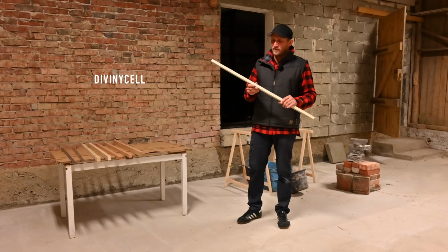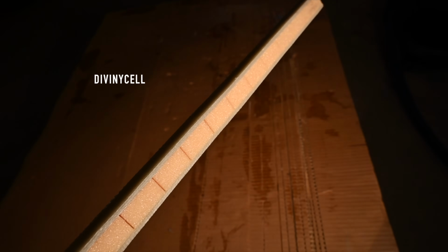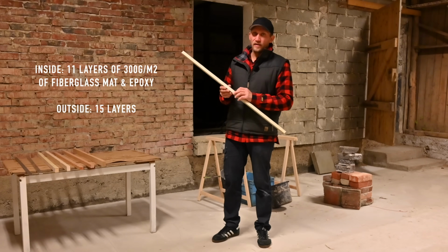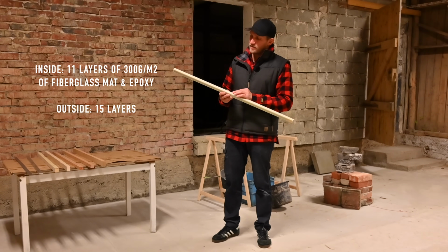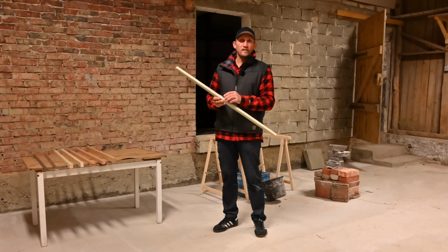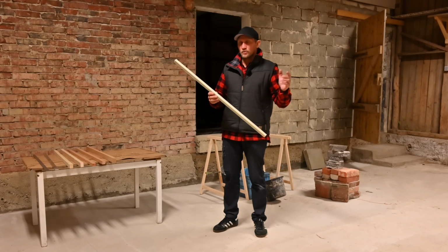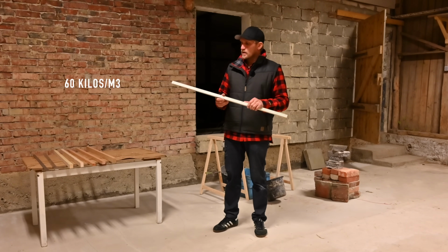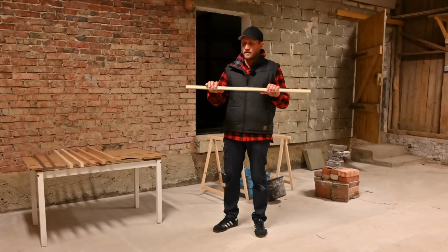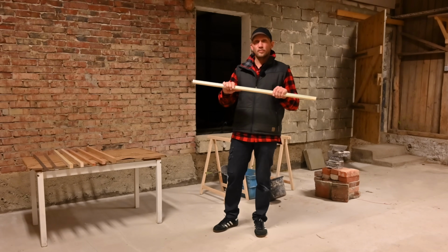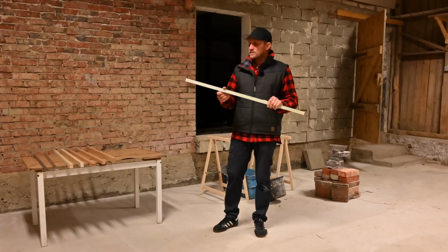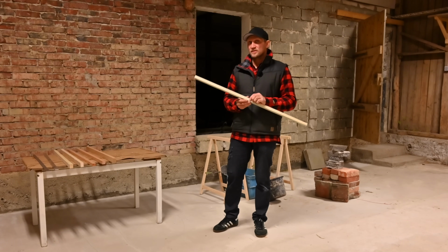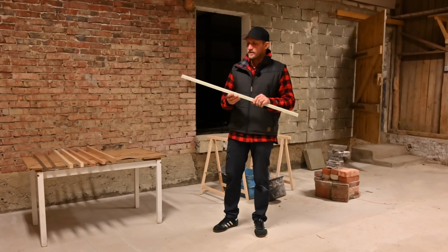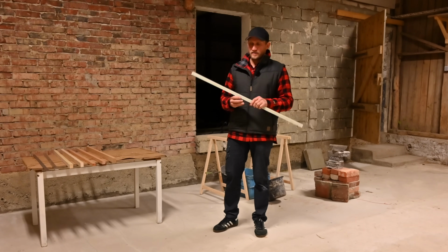Yeah, and last we have the Divinycell with glass fiber and epoxy. On the inside here we have 11 layers of 300 gram glass fiber with epoxy and 15 layers on the outside here. This Divinycell is called H60, which means that 1 cubic meter of this weighs 60 kilos. I would say the main benefit of Divinycell with glass fiber and epoxy like this is that you can build a really light construction with this. Also the core material is rot resistant, but you shouldn't get water in there because you can get other problems like delamination, especially up here in Sweden if it freezes when it has water in it.